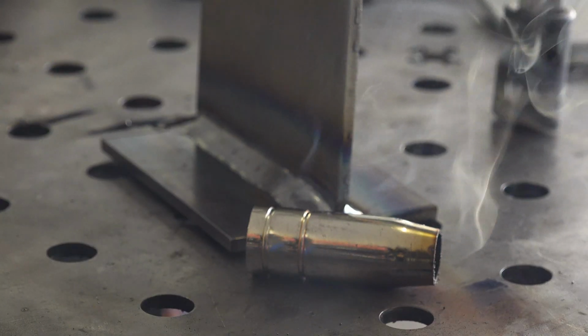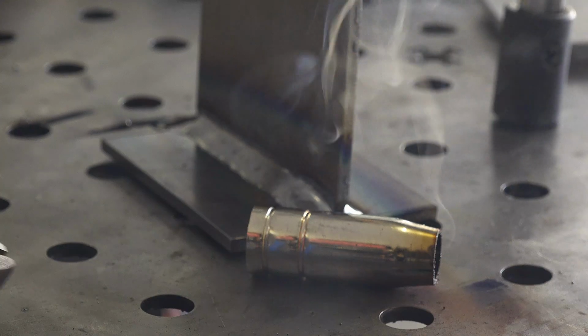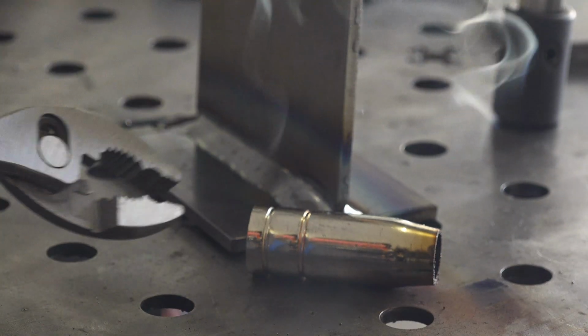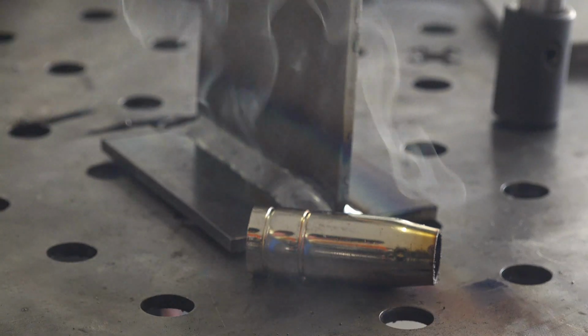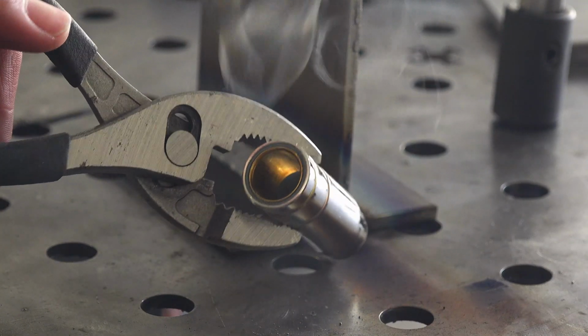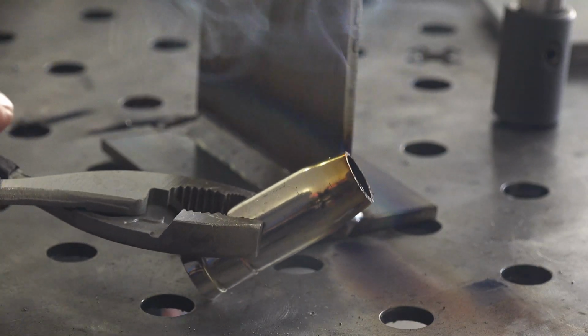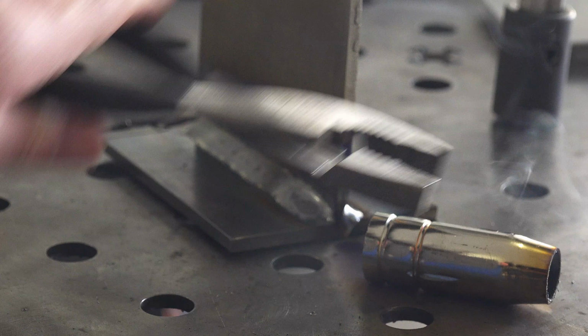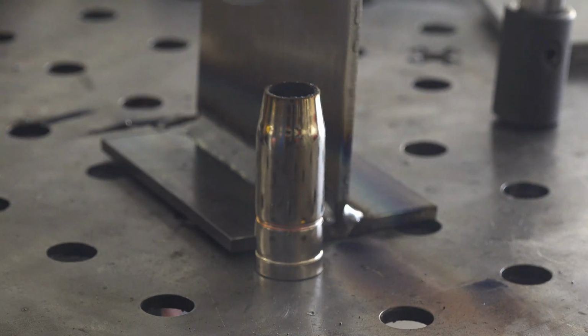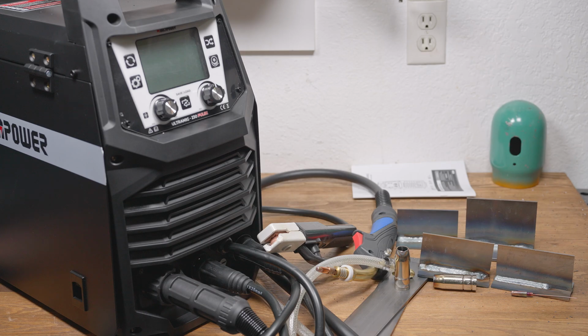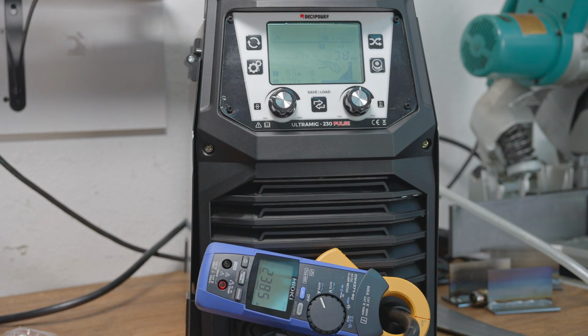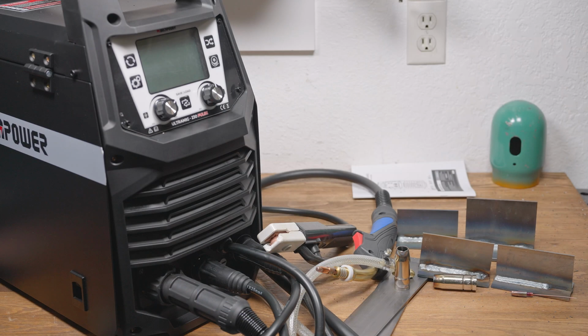So apparently running pulse, which is a spray process, as I've said, is quite hot. Running pulse for just maybe a 3 to 4 inch bead will basically set the nozzle on fire, essentially. There is an insulating layer between the outer metal and an inner metal sleeve, and that layer was smoking heavily after just a short weld at max output, which interestingly wasn't 230 amps, but slightly over 250 when maxed out in pulse mode. But even when turned down to between 170 and 200 amps, the nozzle was still overheating after just a few inches of welding in pulse mode.